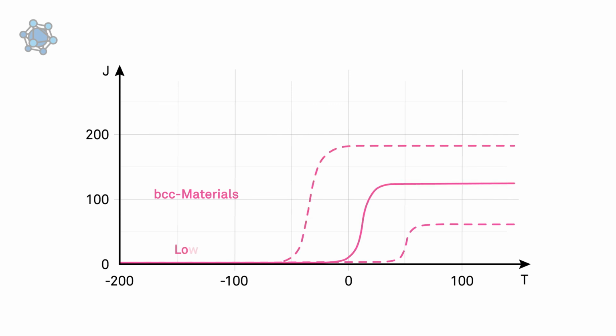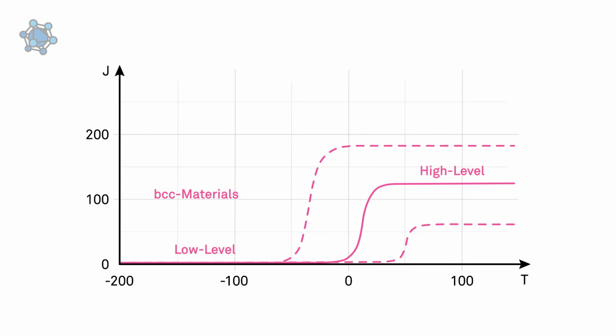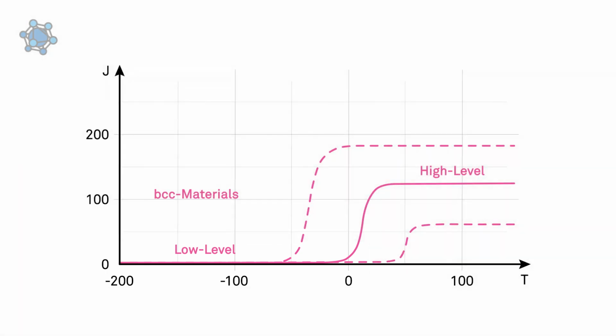Let's now look at the temperature dependence in the Charpy Impact Test. The test is not only performed at room temperature. Materials with a body-centered cubic structure show a strong temperature dependence in their V-notch impact work and exhibit an S-shaped curve with a steep slope. This is referred to as the transition temperature. In the upper shelf, the same material can absorb a large amount of V-notch impact energy. In other words, at this temperature range it's tougher and has more of a ductile fracture. In the lower shelf, it's more brittle and can absorb way less impact energy.